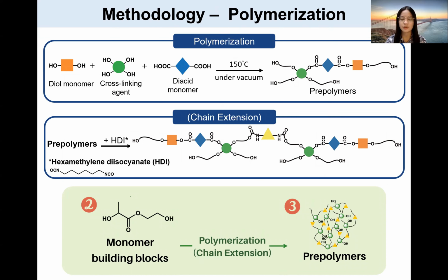So in the polymerization step, I've tried 2 methods, and both are successful. The one is without chain extender but with catalyst. The catalyst is zinc acetate. And the other one is with chain extender but without catalyst. So here it is important to note that the chain extender is used for increasing the molecular weight.